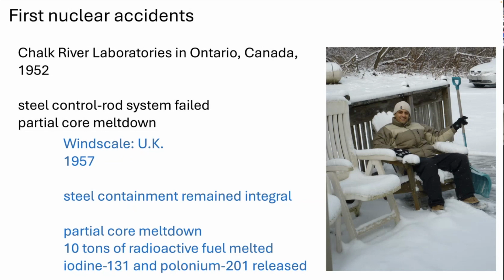The second disaster was in Britain, in the Windscale, and this was much more serious. It was in 1957, where the steel containment of the reactor remained integral. But the reason for this disaster was interesting, that irradiation causes damage in the metal surrounding the nuclear fuel. Fast neutrons will displace atoms out of their normal equilibrium positions and so forth. So periodically, you actually anneal the reactor by allowing its temperature to rise so that the defects are removed effectively. And that's called annealing, and it releases an energy known as a Wigner energy.